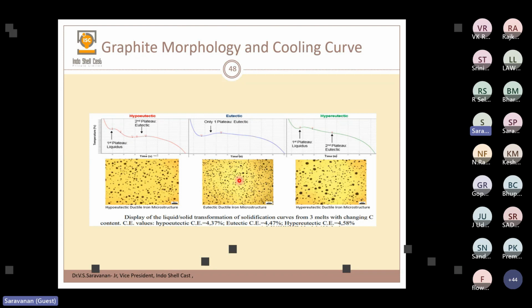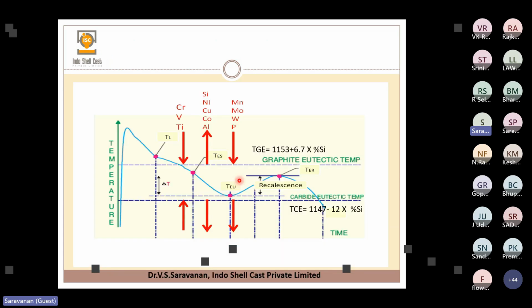we can see which is the hypereutectic metal and which is the eutectic metal, and the thermal analysis curve shows those things. One more thing: this is the graphite eutectic temperature, and this is the carbide temperature. They derived this particular line. It is actually a virtual line, a virtual boundary. They have a formula for that. In this boundary we need to have this TEU and TCR. If it exceeds like this, then there is a problem.